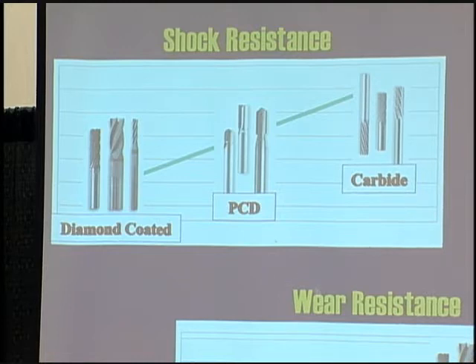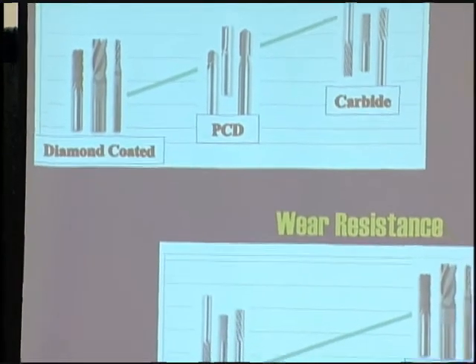The downside is when you go to the wear resistance, which is usually the biggest problem in machining composites. You wear out tools very quickly. The PCD and diamond give you the greatest wear resistance. So the better you can get that fixturing, the less the part vibrates, the more successful you'll be with tool life by utilizing diamond coating and PCD cutters.